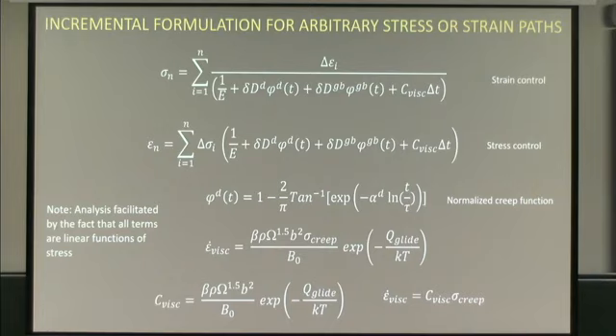Now you have to integrate back considerable ways until each one of these steps is exhausted to get the full answer, which would be one of the areas I think that math folks, if you can come up with a more efficient way to handle the hereditary integrals, I would love you forever. That'd be great. And conversely, if you're in stress control, you'll have increments in stress, and then you just multiply that by the loss compliances to come up with the strain increments as a function of time. And so you do that for each of these loading increments. The viscous, I just pulled out stress here to get a different term, so we can factor out stress since they're all linear. Piece of cake, a little bit of programming, but again, a bit of a computational burden here to handle the hereditary integrals.